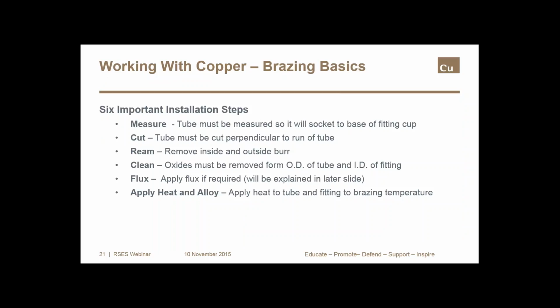Here are 6 installation steps that will ensure an effective brazed joint: measure, cut, ream, clean, flux, and heat. All of these steps are important. The tube must fit all the way into the base of the fitting cup, so measuring the tube is critical. The tube must be cut so it's perpendicular to the tube run, and then any burrs must be removed.